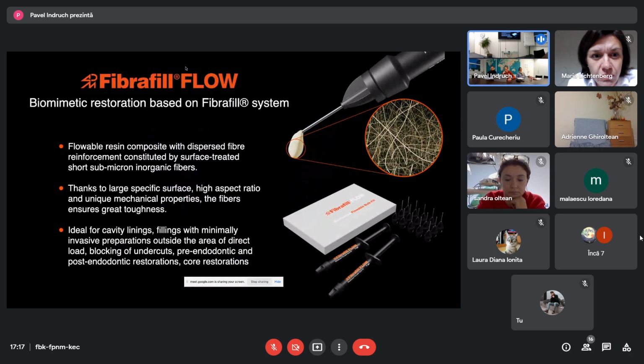Complements to the Filla Cube are two other materials, which maybe will be more familiar to you because they are more similar to conventional composites than the Filla Cube. One of them, called Fibrafil Flow, is hybridized with dispersed fiber reinforcement constituted by surface-treated short submicron inorganic fibers, which work kind of like a three-dimensional net in the bulk of the cured material. Thanks to a large specific surface, aspect ratio, and very unique mechanical properties, these fibers ensure a great fracture toughness of the material. The flowable material is ideal for cavity linings, minimally invasive fillings, and, for instance, blocking of undercuts if you replace old amalgam fillings.